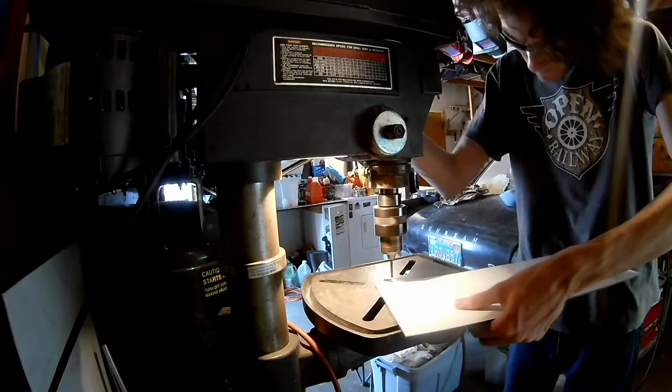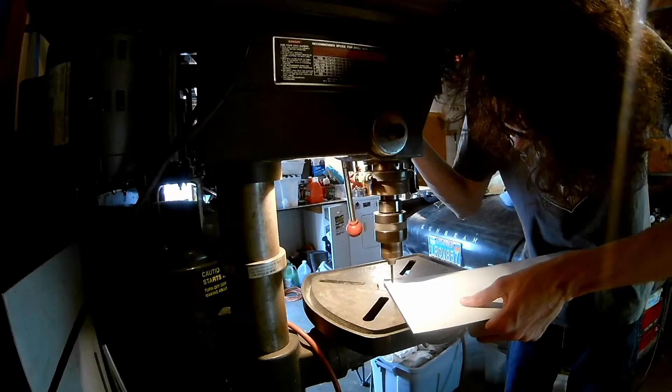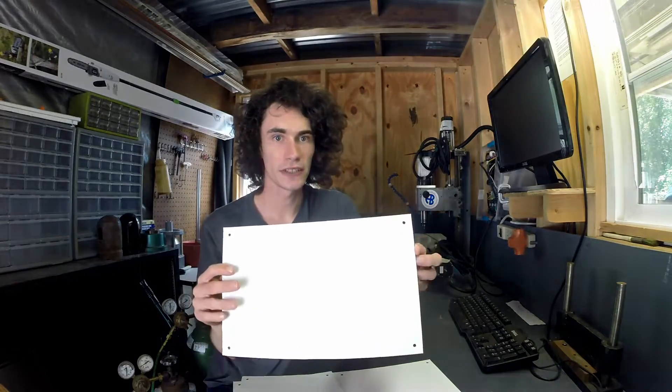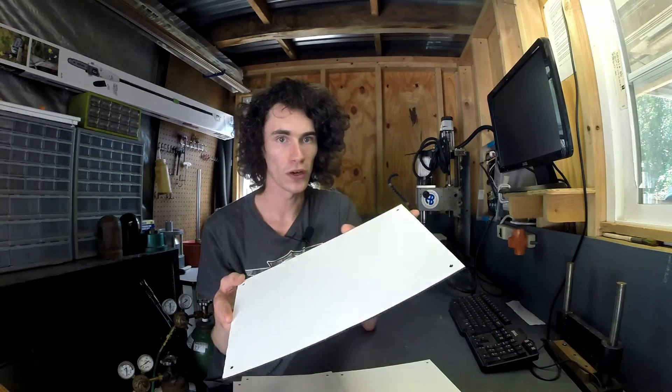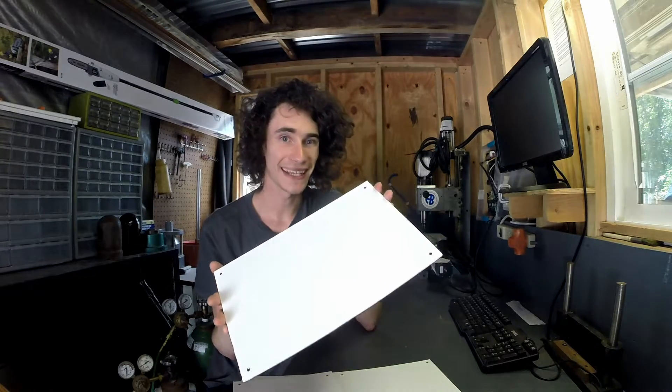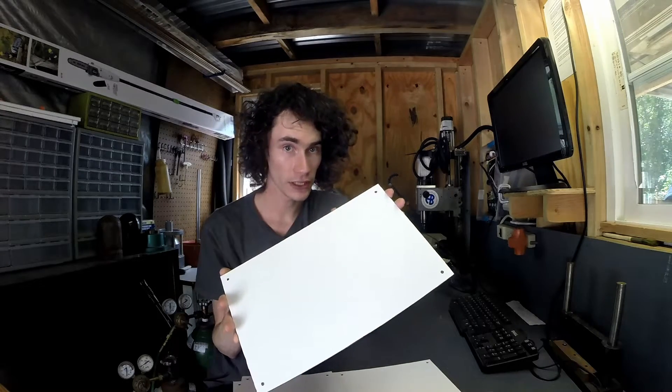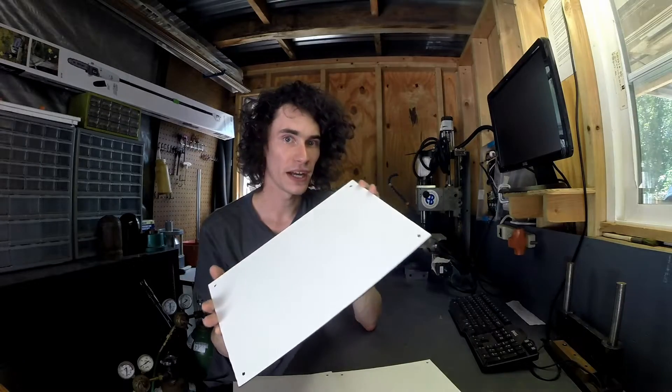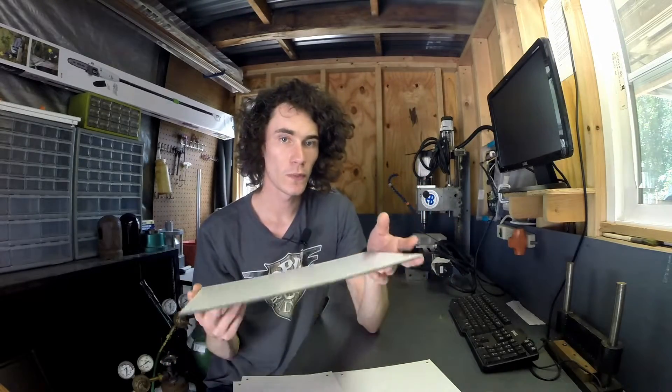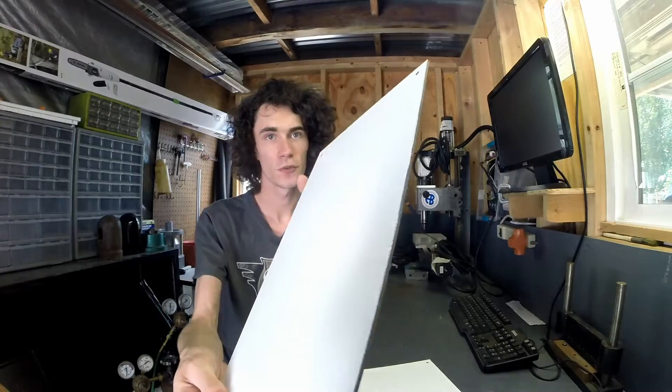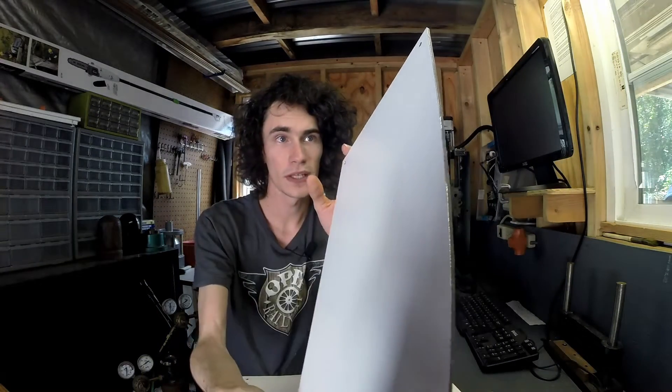Now when it comes to drilling it, same story, just keep a low drill speed and use a sharp bit and it goes through easily. Do note, though, that when you are deburring the material, because it is so soft and it has that plastic core, deburring it can be somewhat hard to get a really nice clean edge. If you're going to route this, I highly recommend just running a fast deburring pass. If you are going to deburr it by hand, just take your time and maybe use a file instead of one of those burr whip tools. I used a burr whip which worked, but there's some edges where it's a little bit rough where the burr whip started to actually cut in a little deep and it was a little bit hard to correct for that, but overall it works pretty good.